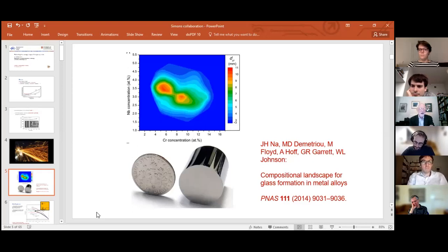How it would crystallize is quite dramatically different from glass to glass. So at one extreme, they only show nanocrystals. At the other extreme, they show millimeter scale crystals that are perfectly evident to the naked eye. So you get a vast spectrum of behavior depending on the relative rates of crystal nucleation and growth. I see. Okay, thanks.